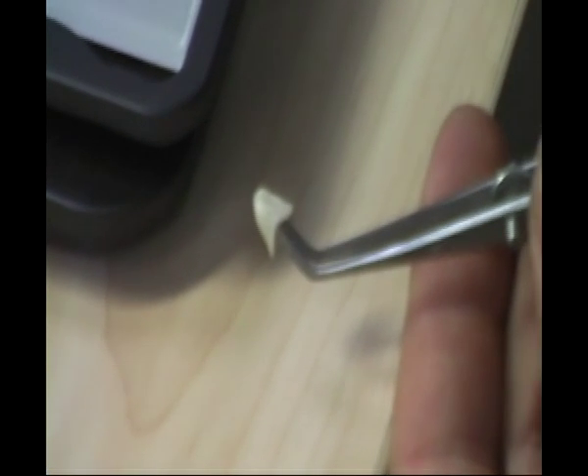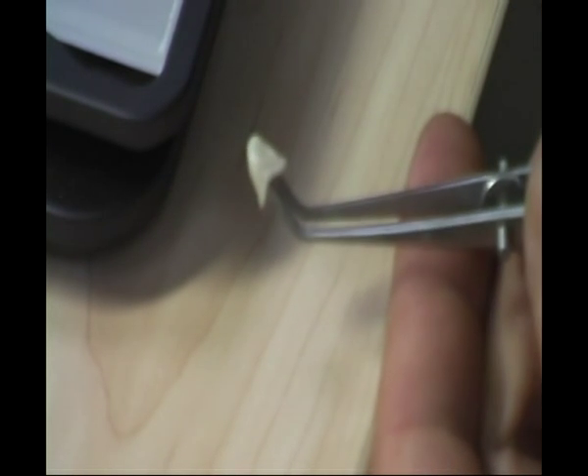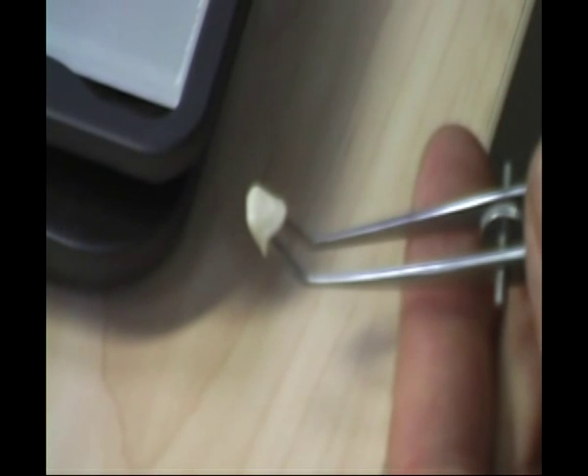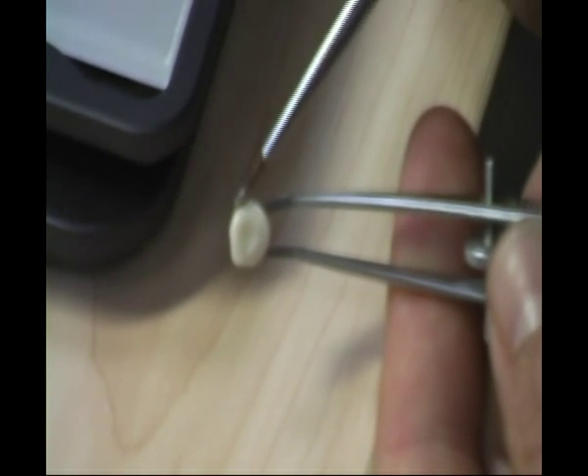Normally zirconia has no natural tooth fluorescence. This neutral frame shade has no color, but once applied it increases retention and fluorescence. It makes only a layer of 0.3 millimeter at most, which is fluorescent and gives us a connection to the ceramic. It also enhances the bond with the zirconia ceramic powder. We fire this at 860 degrees, holding for one minute.